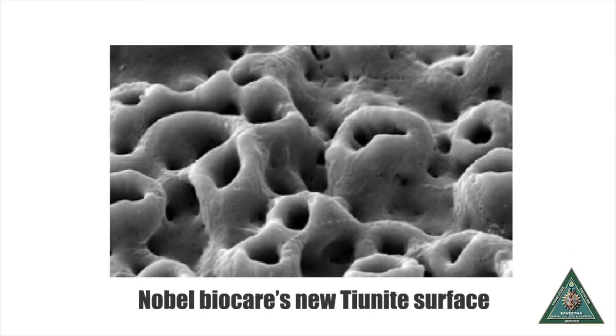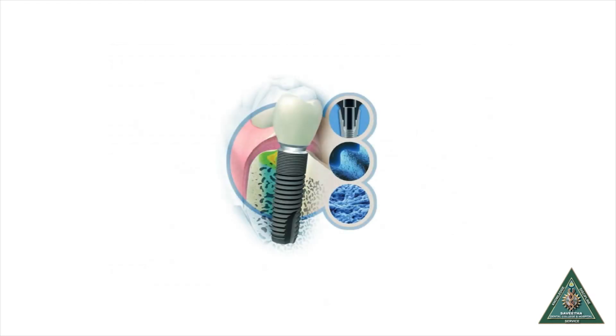Additive texturing has been phased out of use due to increased chances of delamination of the coat. Nobel Biocare's new TiUnite surface uses a patented procedure that many believe is a combination of anodization and subtractive texturing. Subtractive characterization is used predominantly as it is cheaper and easier to perform. The etching process is used to create surface roughness; companies using this process include Astratech, where they use hydrofluoric acid for their OsseoSpeed surface.